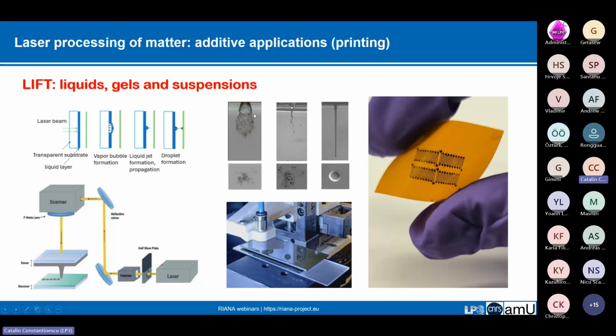So coming back to the jets, a process window needs to be carefully defined. So for that matter, if the energy is too high, the energy of the laser will destroy the bubble. If it's too low, the jet will not form properly. And if we are in the proper parameters, the process window, then we can get a jet and therefore a droplet. And with this in mind, we can use the droplets either to print one next to the other or one over the other, and therefore create from droplets to continuous lines. In this case, we printed some structures, the meanders, that can be used for various applications.